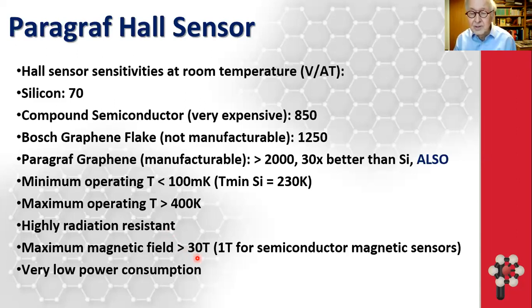That opens up new fields that the graphene Hall sensor can be used in, for example in fusion reactors. Our Hall sensor is now being tested in fusion reactors, which have these very large magnetic fields, like tokamak type reactors. Another remarkable property is very low power consumption, because the resistivity of graphene is so much less than the resistivity of silicon. Our power consumption, in fact, is 1,000 times less than that of a silicon Hall sensor.